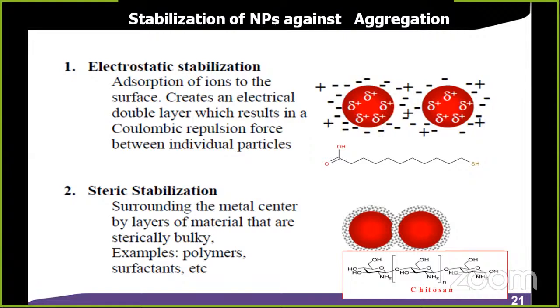If it is lesser than 20 millivolt, the particle is going to aggregate. Therefore, you have to do the surface modification. So we have to take stabilizing agents or ligands appropriately, and you should stabilize the nanoparticles. Sir, if we prepare the nanoparticles without adding ligand, will it be stable? It will not be stable even for 1 hour. If we check the zeta potential, it will come less than 20 millivolt only. That is why it easily aggregates.